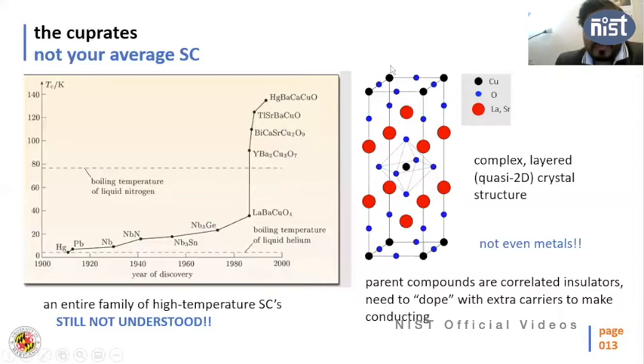So in terms of theory, we say there is a very weak correlation between these two planes. That means if you measure the resistivity along the c-axis, it will be very high compared to the resistivity in the AB plane. This is the reason we call these materials quasi 2D. These are complex, and this is also the layer structure.